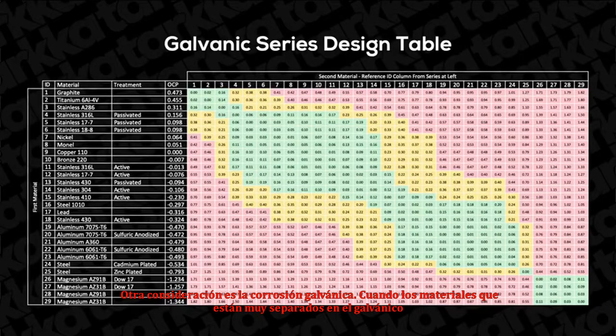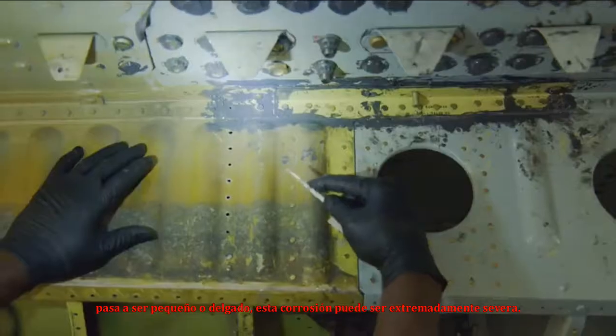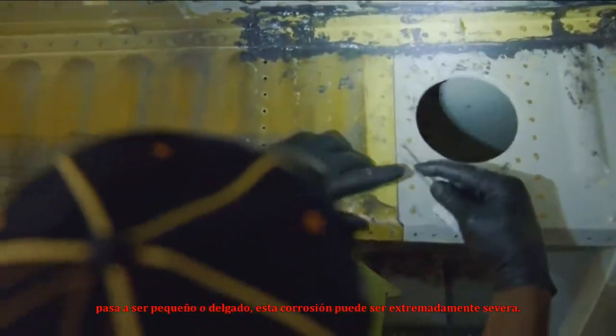Another consideration is galvanic corrosion. When materials that are far apart on the galvanic series are in contact and in the presence of an electrolyte, a galvanic cell is formed. In this case, accelerated corrosion occurs on the more anodic material. If the anodic material happens to be small or thin, this corrosion can be extremely severe.